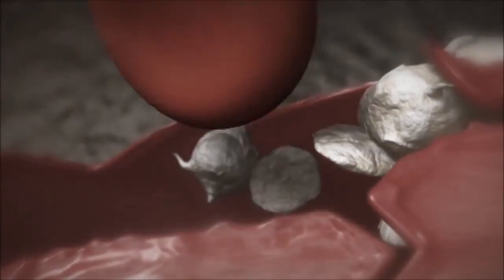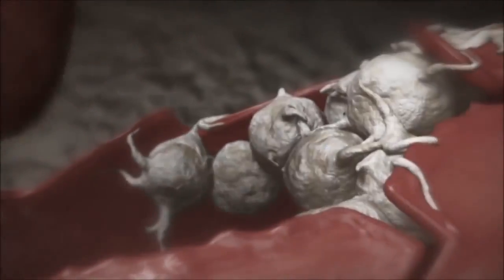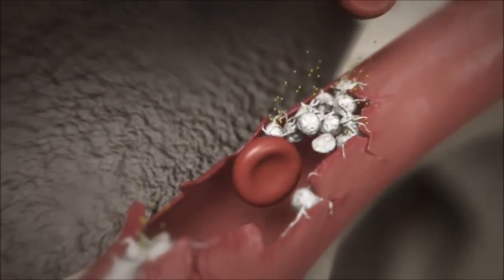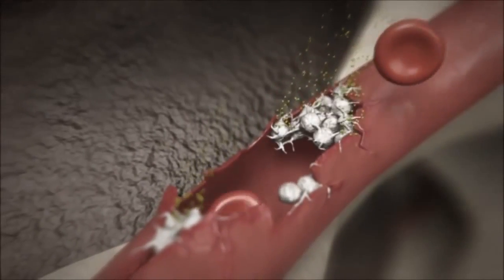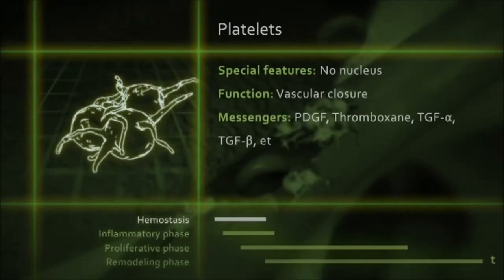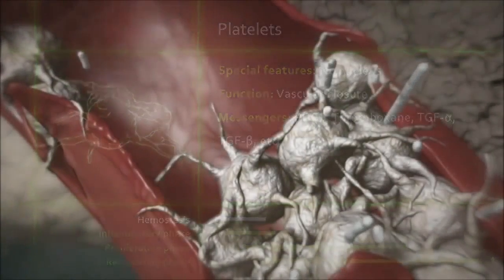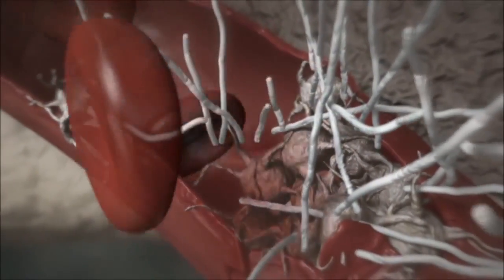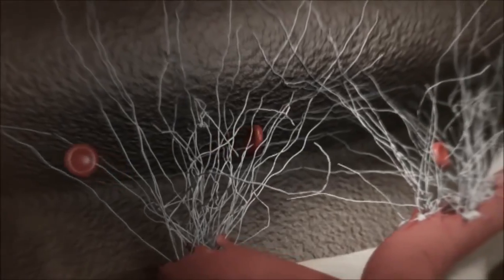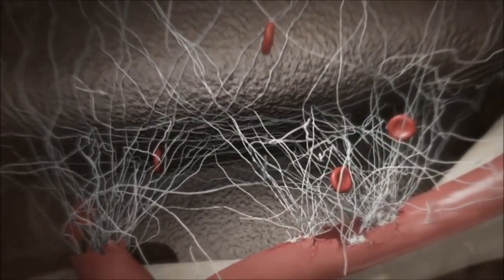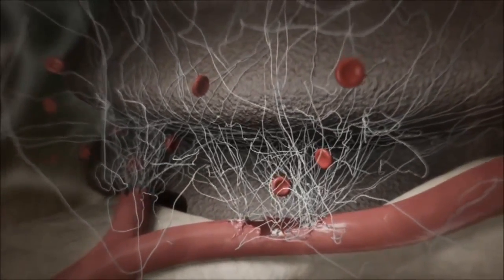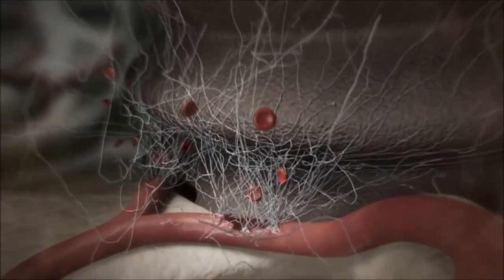Next, the bleeding is stopped by blood platelets, also known as thrombocytes. When they are exposed to collagen and other proteins from the traumatized tissue and implant surface, they aggregate and close the ruptured blood vessel. Platelets release various messenger substances for cell-to-cell communication, such as thromboxane, which promotes platelet aggregation, or PDGF — platelet-derived growth factor — which stimulates the cell division of fibroblasts. Fibrin monomers spontaneously cross-link forming a fibrin network. The blood clot permeates the wound space, forming a provisional matrix, and also adheres to the implant surface. This blood clot has tremendous importance as a provisional matrix for subsequent bone healing processes on the implant surface.